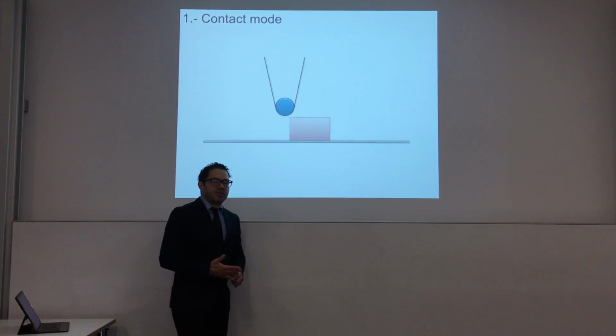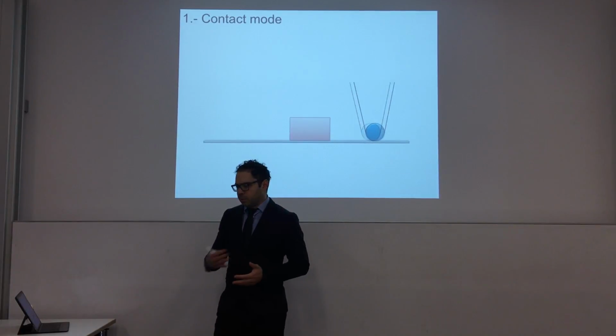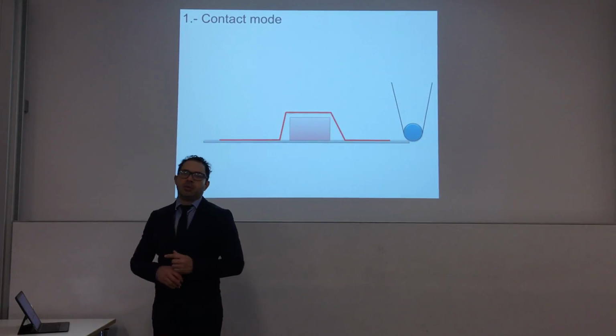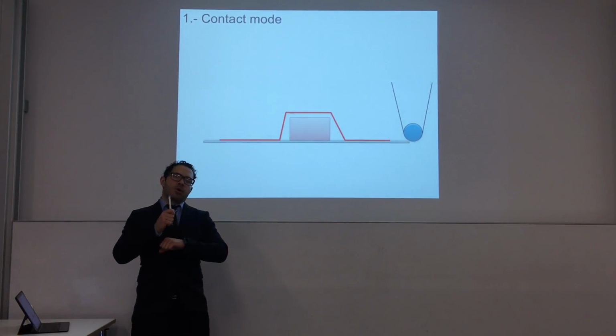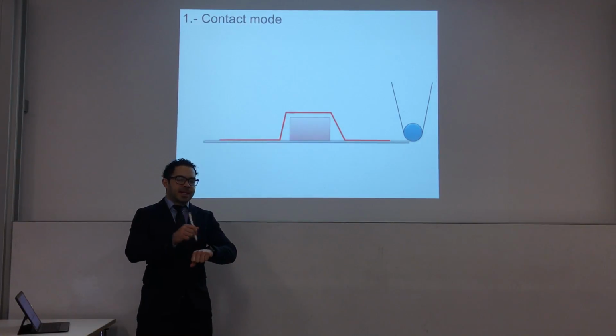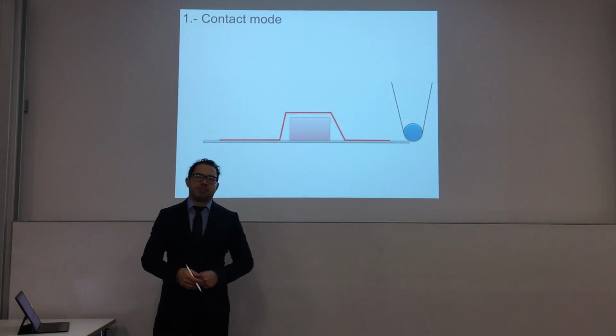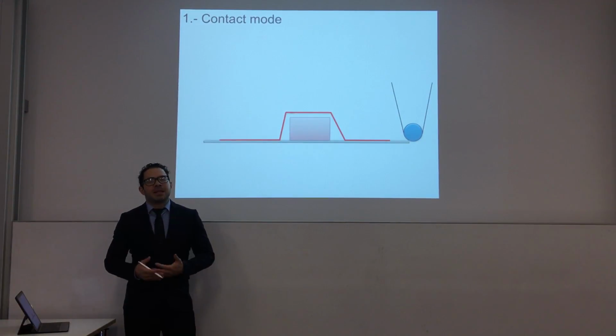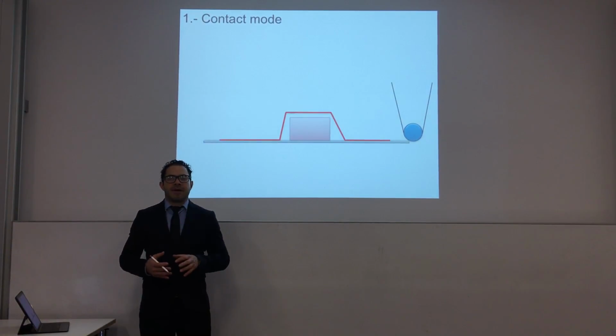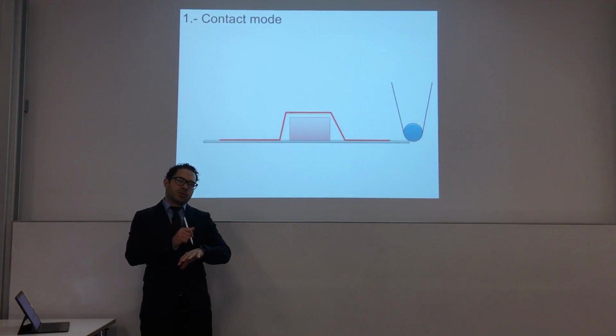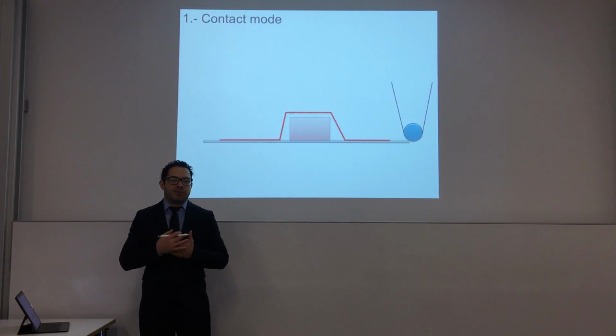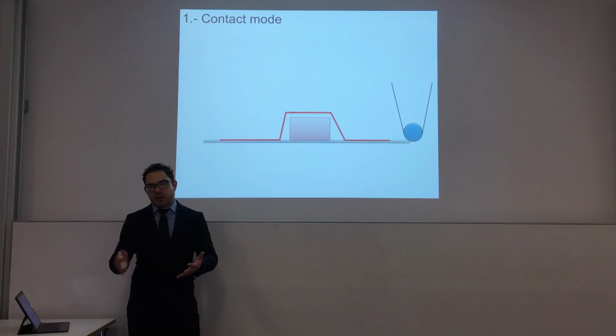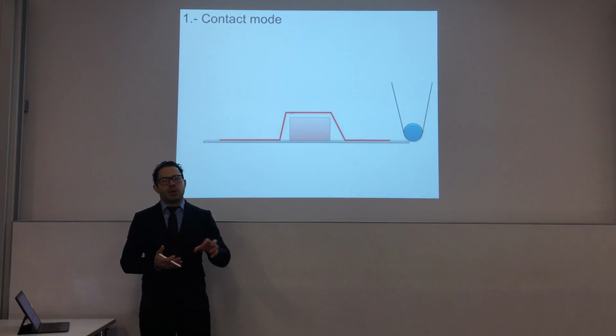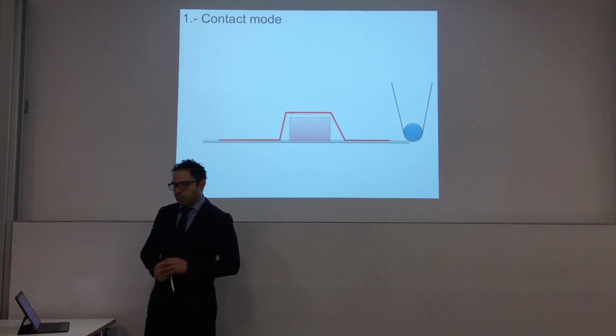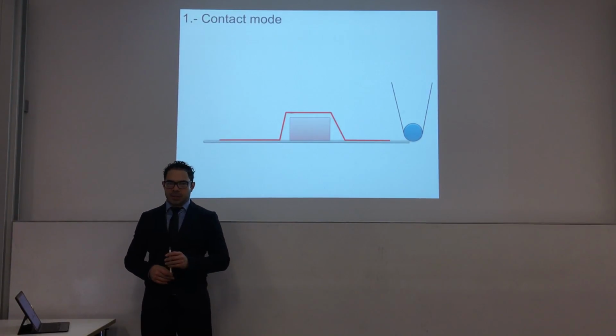The way atomic force microscope works, there are two typical ways. One is called contact mode, in which your tip is in constant mechanical contact with your sample, and it scans pixel by pixel, line by line, as I explained before. The disadvantage of this method is that you will have some strong force. The force is continuous on the sample, so that if you have a material that is very soft, you can deform it. Or if you have material that is not very well attached on your substrate, then you're dragging around the material. It will be hard to analyze using this method.